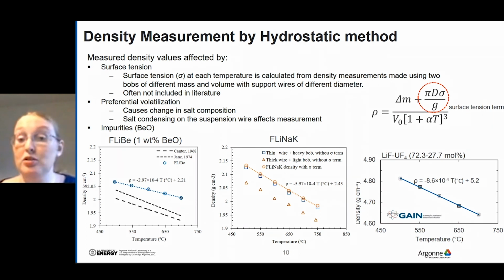So that is illustrated with the middle figure here for FLiNaK, where we took measurements in the red triangles with maximized surface tension effect, so a thick wire and a light bob. And then we took measurements with a thin wire and a heavier bob, the blue squares, which kind of minimize that surface tension term. And we were able to set those data points equal to each other because the density of the fluid is the same, and obtain the surface tension value, and then back correct all the values to the real value, the orange circles.